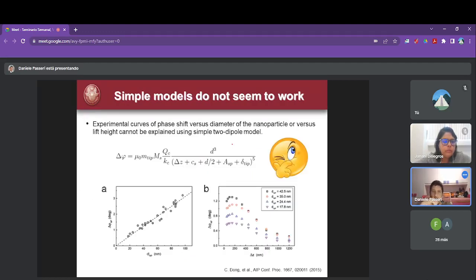And the most upsetting thing was that we repeated this experiment many times, and the results were always coherent, but always contradicting our simple model. We obtained this linear relation, which is not foreseen. Here, okay, there is the decay we would expect, because this is as a function of the lift height, and so here there is the fifth power, and it is 1 divided by this. But why this strange result? This is not easily described.